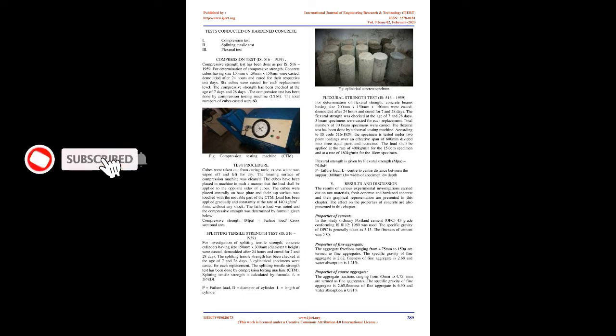Chandrasekhar Reddy et al., 2017, investigated the durability of concrete by replacing sand with quarry dust and cement with fly ash. The natural sand was replaced by quarry dust in steps of 0%, 10%, 20%, and 30%, and cement by fly ash in steps of 0%, 10%, 20%, and 30%.